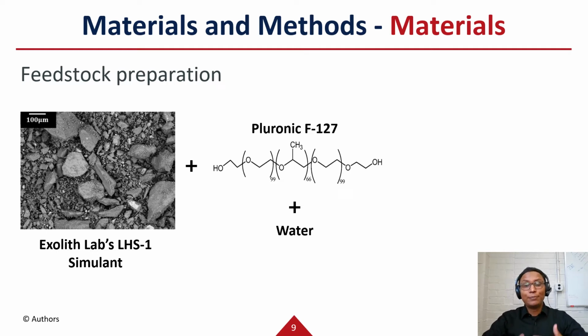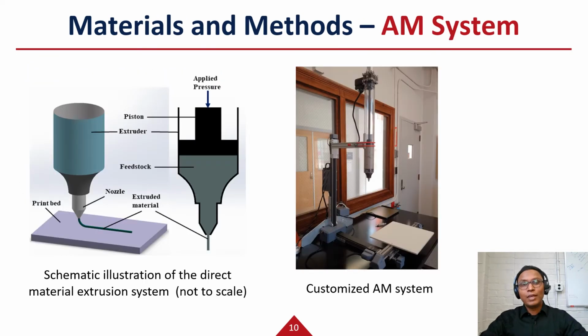It was added to the pluronic solution in 2 steps, with each one followed by mixing at 600 RPM in a planetary ball mill for 2 minutes. We also carried out a final mixing to get a homogeneous mixture. We modified a commercially available ceramic 3D printer and used it for manufacturing structures and parts. We adopted this direct extrusion-based AM system for its simple design, ease of operation, and the minimal requirement of operators' training and maintenance, which will come in handy for potential manufacturing applications in space.